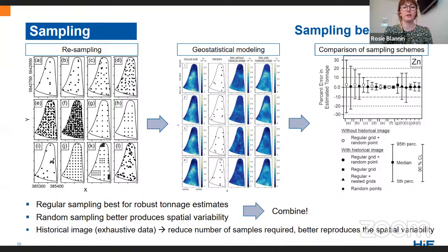And then looking at the configuration of the samples, well, we found that the regular sampling is best for producing robust tonnage estimates, whereas the random sampling better produces the spatial variability. So the regular grids tell us what we have, whereas the random sampling will tell us where we have it. And both of these will be important for properly assessing the resources and deciding how we would remine these deposits. So overall, it's probably best if we combine these two types of sampling.